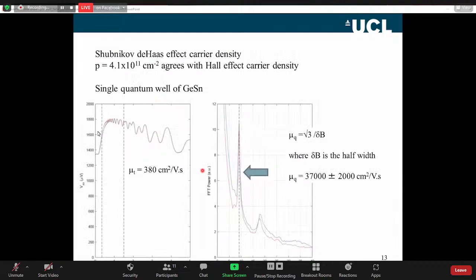This is another measure of the Shubnikov-de Haas effect. If we look at the transport mobility, that's the zero field resistance combined with the Hall effect. The Hall effect gives us about 4 times 10 to the 11 carriers. We can measure the carrier density from the period of the Shubnikov-de Haas effect, and we can measure it from the Hall effect. And in these materials, they agree very, very well. So we've got two different techniques. It tells us that the charge is in the quantum well. There's no charge in the substrate or the buffer layers or on the surface contributing a parallel conduction effect. They're very well behaved two-dimensional hole gases.